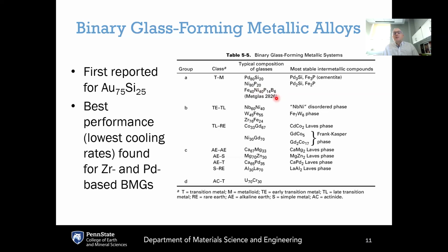A general rule of thumb with metallic glasses is you want to add more elements to your alloy and select the combination of metals where they have mutually incompatible crystal structures, either because they prefer different types of crystal structures, or there's a big enough size difference that they cannot be substituted for each other within a common phase.